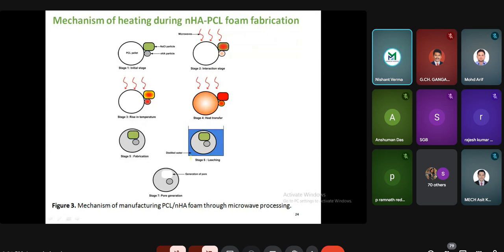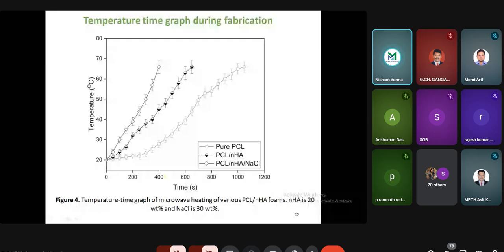And after fabrication, we have done the leaching. Why have we done the leaching? Because we dissolve the salt particles, and after dissolving the salt particles, the pores are generated. Whenever the salt particles are attached to the material, at that place the pores are generated. And an interesting thing is that the pore size is exactly equal to the particle size of the NaCl. So this is all about the PCL nanohydroxyapatite composite.